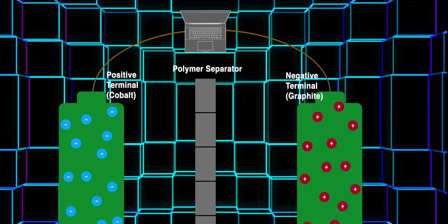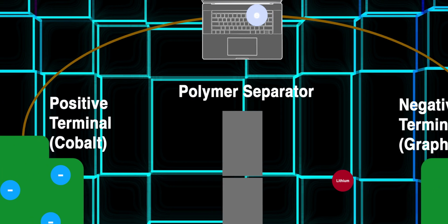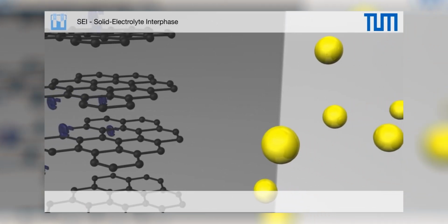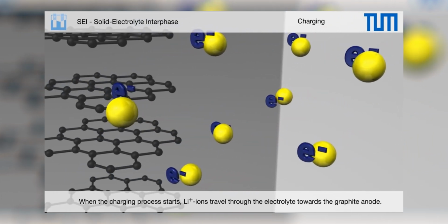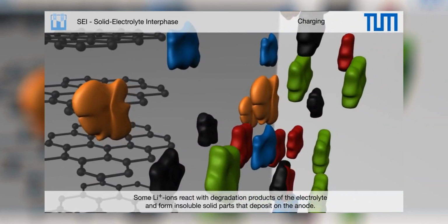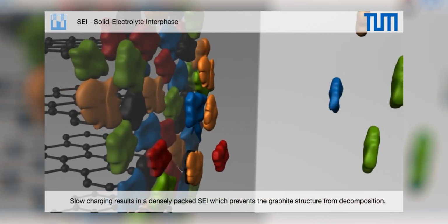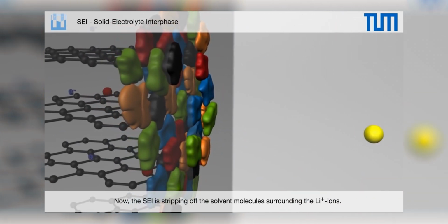So why do batteries degrade at all? Each time you charge and discharge a battery, in your phone or your computer, lithium ions move from one side of the battery to another. When discharging, they move from the negative terminal, also known as the anode, to the positive terminal, known as the cathode. What happens over time is that internal resistance increases in the battery, and more voltage is needed to charge the cell fully. On the negative terminal, there's growth of solid electrolyte interface, or SEI, which is a barrier that obstructs interaction with the graphite, as well as lithium plating on the surface caused by high charge rates. On the positive side, electrolyte oxidation is formed and leads to capacity loss.